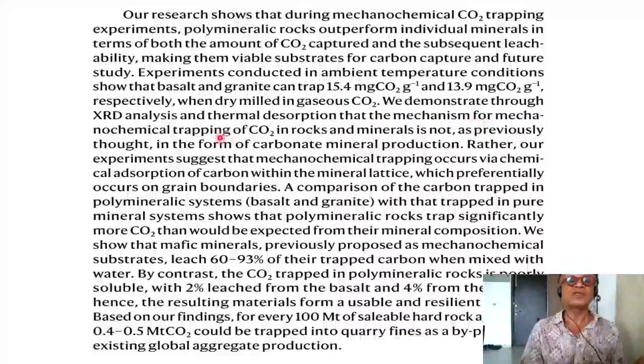We demonstrate through XRD, X-ray diffraction analysis, and thermal desorption that the mechanism for mechanochemical trapping of CO2 in rocks and minerals is not as previously thought in the form of carbonate mineral production. Rather, our experiments suggest that mechanochemical trapping occurs via chemical absorption of carbon within the mineral lattice, which preferentially occurs on grain boundaries. A comparison of carbon trapping in polymineralic systems like basalt and granite with that trapped in pure mineral systems shows that polymineralic rocks trap significantly more CO2 than would be expected from their mineral composition.